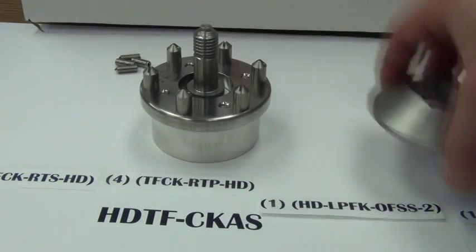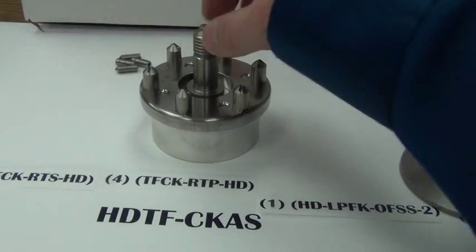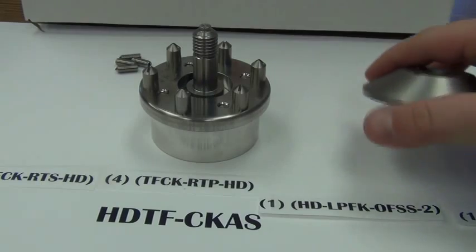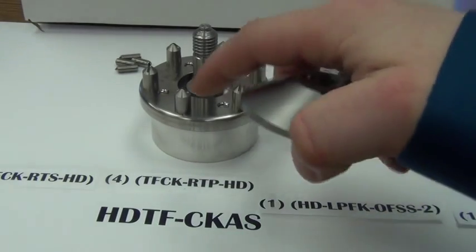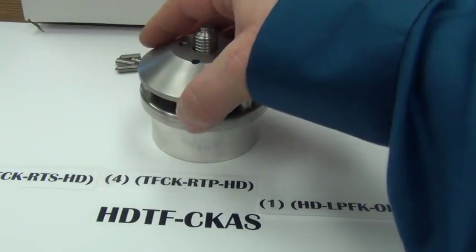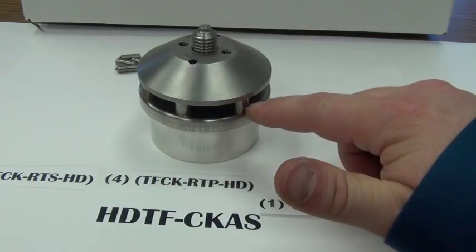So you'll set your lamination up as you would a normal bulldog lock over top of this dummy and setup, tie it off around the center post, push it so the layup sticks through the spikes, and then put this cap on top of it. And this center in between here will make the distal end of your socket.